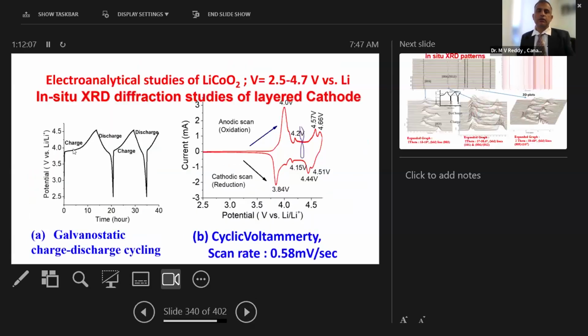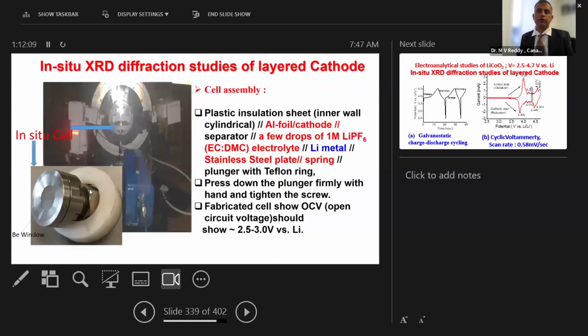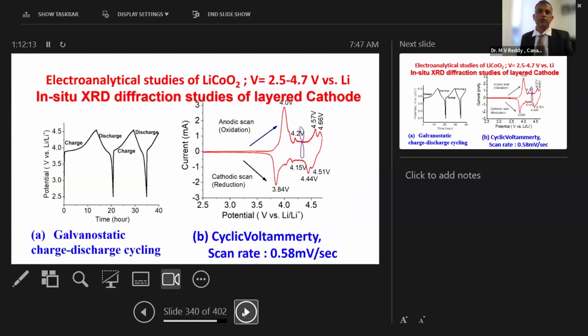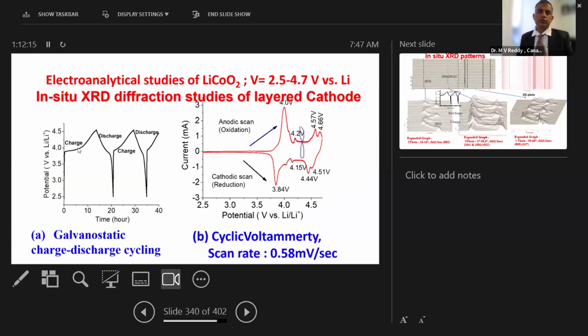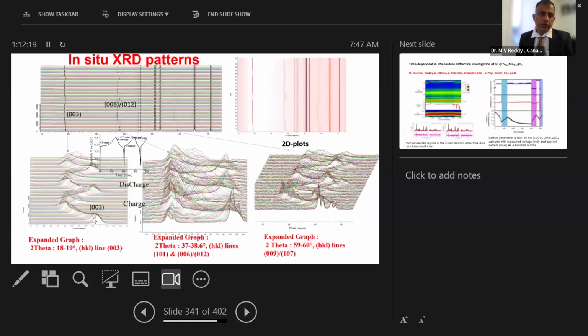So I told you that with real-time XRD, we take the real-time battery while running the X-ray patterns. As you can clearly see, we stop the batteries and take X-rays at different voltages. When you remove the lithium, the volume changes, which means that 2θ is going to lower angle. As a consequence, there is a volume variation, a variation of the lattice parameter. So contraction and expansion are occurring.